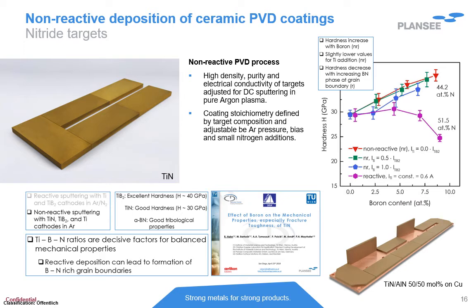Let us have a look at the diagram on the right side, showing the hardness as a function of boron content measured in the deposited coatings. The boron content was set by changing the power applied to the titanium diboride target. If we follow the magenta curve in the diagram, standing for the reactive sputtering mode, the hardness increases slightly up to a boron content of about 5% before it drops down with higher boron level.